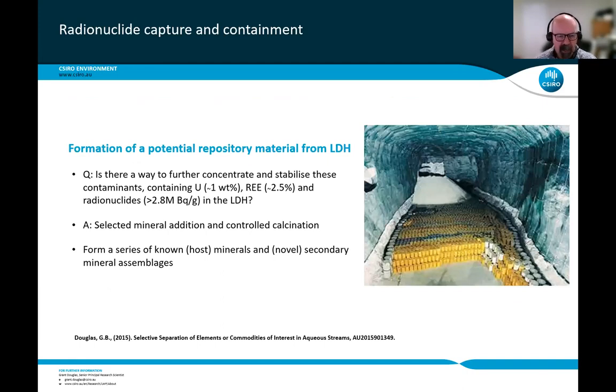Okay, I'd like to move on now to the last example I've got, which is the formation of a potential repository material from layered double hydroxides. And so the question we posed to ourselves there was, was there a way to further concentrate and stabilize these contaminants in this quite enriched, I use enriched not in an isotopic sense, but enriched in terms of an element sense, layered double hydroxide? And we did a lot of work around this, and the answer was either selective mineral addition, or in the simplest way, just controlled calcination leading to the amorphization of the layered double hydroxide.